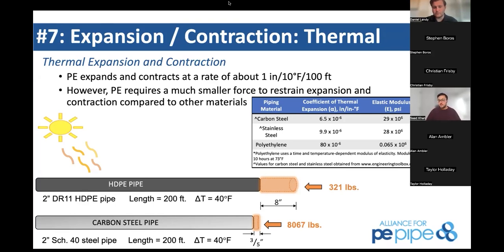And so the reason that this is important is when you have buried polyethylene pipe systems, the ground typically offers enough force around it to restrain that pipe to prevent any expansion or contraction. The only place that you need to pay close attention to the expansion contraction is, one, if the pipe is above ground, or two, if the pipe is terminating at a rigid end connection above the ground. And there are very simple ways to design for that, which we can talk about later.